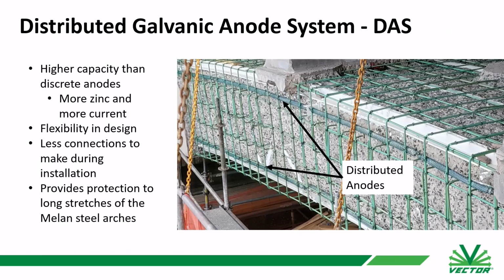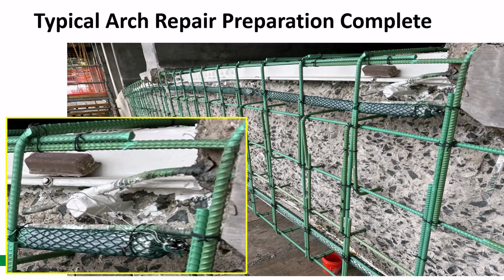And so a lot of that steel is still embedded in the chloride contaminated concrete. And so in this situation, they used a combination of these long distributed anodes, similar to what we showed for the ODOT abutments, but they basically follow the arch, and that's designed to provide all the protection to the uncoated areas of the steel. So the areas that may have holidays in the coating, but also the parts of the structure that are still embedded in concrete.